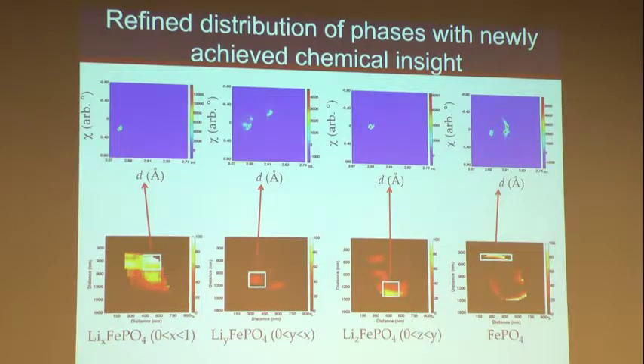You can assign a 2 theta and a composition. And so what I'm showing here is what domains light up when you're integrating your signal at a different angle. And so it tells you where lithium iron phosphate is, where iron phosphate is, and where the intermediate compositions are. And so if you look, and remember what I was just showing you, there is a trend for the iron phosphate to be at the edges, the same thing that we saw in the TXM measurement. But now what we see is that on the inside, where we thought we had domains, where we had 2 phases mixing, in some cases, it's actually 1 phase with both oxidation states in the same unit cell.